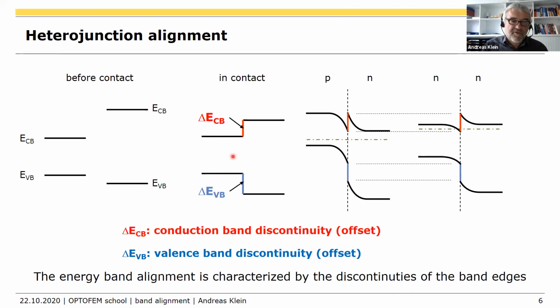But of course, like the Schottky barrier, where the Fermi level can in principle vary through the whole band gap, you can also have the valence band and the conduction band discontinuities vary quite strongly. So you can in principle have the conduction band down here very close to the valence band. That's also something which is possible and which appears.